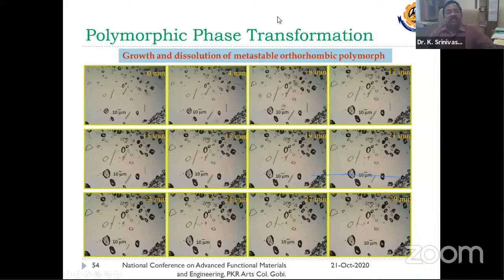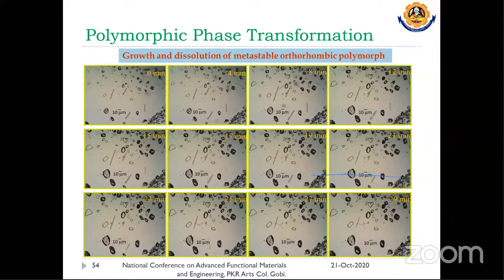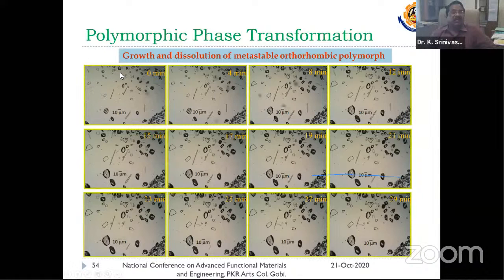Right. So how will these forms transform from one to the other in a solution medium? After the nucleation, see here both the forms exist. These are monoclinic crystals, and the needles are orthorhombic. See, both exist here together. After 4 minutes, 8 minutes, it's continuous microscopic photography, in situ observation. See here, both the polymorphs do grow in size. And after 15, 17 minutes,